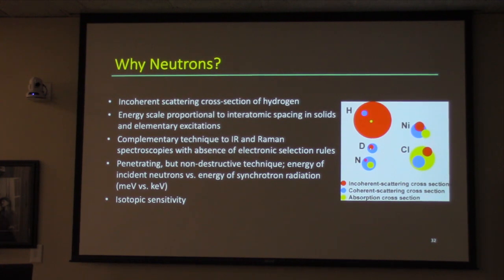Neutrons scatter from materials differently. And the real advantage is that they scatter from hydrogen and deuterium in a really special way. So I tried to show you the comparison between the scattering, the absorption, and the incoherent scattering cross-section. And the one that you should really look at, this is spin incoherency, is hydrogen itself. And that's what makes it so attractive to do inelastic neutron scattering with. Okay? And that's kind of what matters.